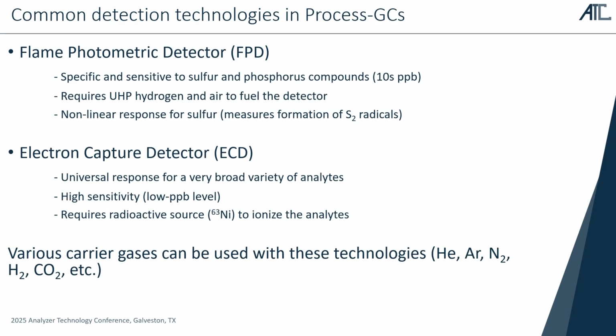You also have detectors like the FPD, that are very specific to sulfur and phosphorus compounds, or the ECD, which is a very sensitive and almost universal detector that you could use, but it requires a radioactive nickel source, which is not very convenient for worldwide distribution or for end-of-life disposal. But still, with all these detectors, there's one big advantage, which is that you have a broad choice over the carrier gas that you can use, while in the case of,